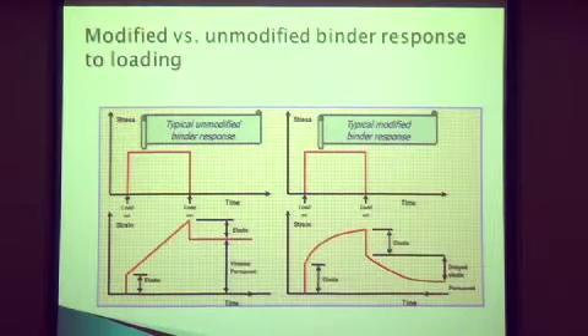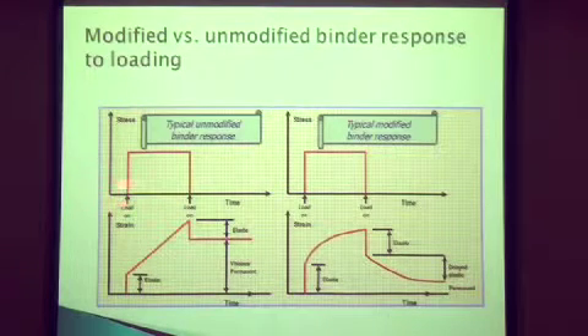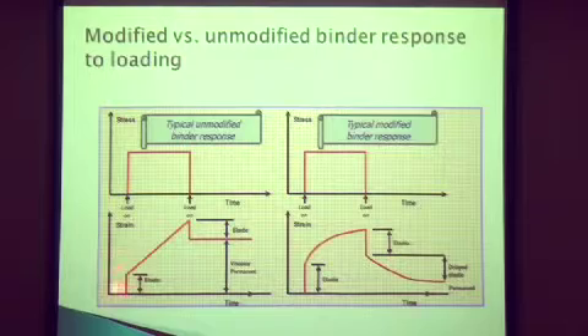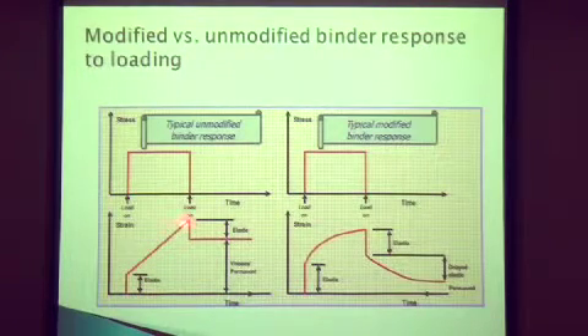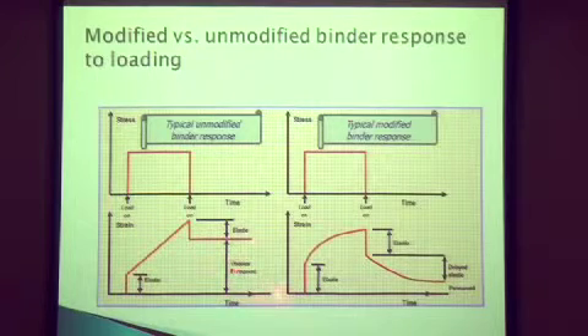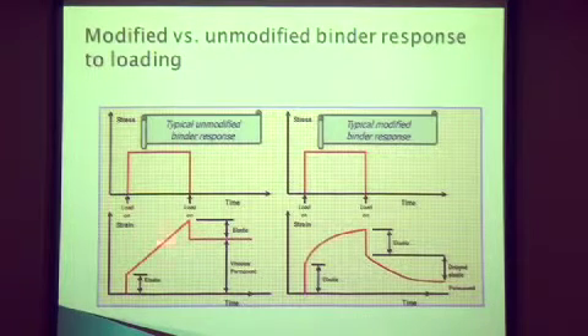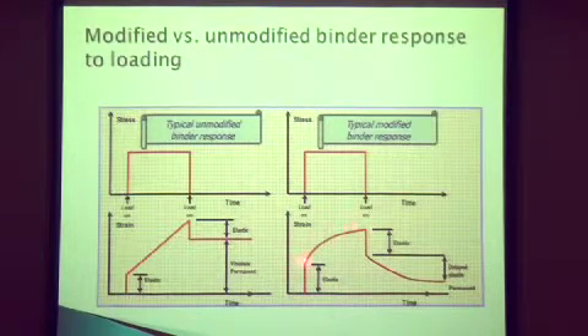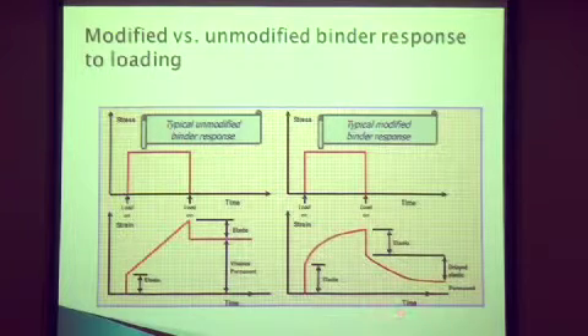Now, in terms of a viscoelastic liquid, what we mean is, if we look at this graph, if I load a binder, take the load off, I get some elastic deformation, I then get some viscous deformation, take the load off, I get a bit of elastic recovery. Here I get permanent viscous strain. So here, this is a viscoelastic liquid. A very simple model, model this with a simple one-element Maxwell model. Typical binders are a bit more complicated. You see here I've got an elastic response, viscoelastic creep, elastic recovery, viscoelastic recovery. I've still got permanent strain. It's still a viscoelastic liquid. And most of our binders will sort of behave a bit like this.